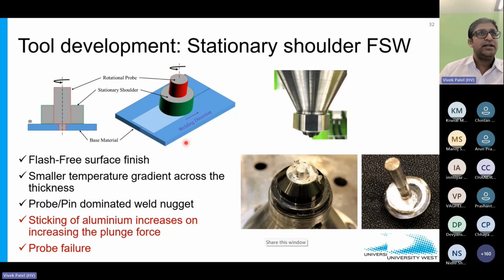But still there are several challenges for the stationary shoulder. Only the probe is rotating, so there is a lot of sticking of aluminum. As a result of sticking of aluminum inside the stationary shoulder, there is a very high chance that the probe gets broken during welding. So you need frequent cleaning. That's, I would say, more work to be done in the case of the stationary shoulder when we talk about production.